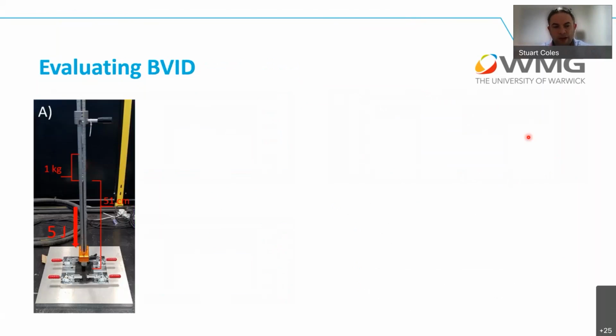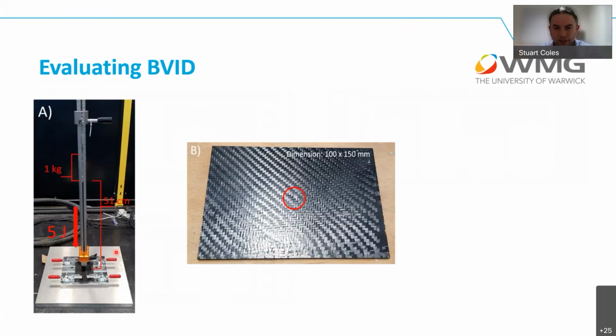But we wanted to evaluate that impact damage, so we developed our own testing kit, which was effectively a 1 kilogram weight being dropped 51 centimeters to give us 5 joules worth of energy, just a little dent on our composite structures. And you can see it is really hard to see. It doesn't matter what size screen you are on or on a projector. There is a very small dimple in that composite that we've induced, and we're looking at that barely visible damage. It's the point of the name, barely visible.